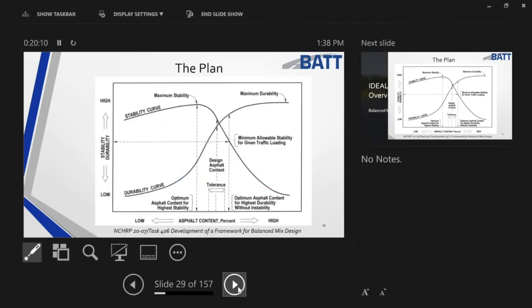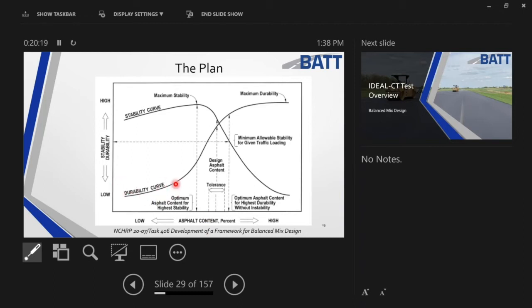This is going to show you the stability curve starting out really high and the durability being really low. If you look at the bottom, I'm looking at asphalt content as I move left to right. As I move to the middle, you see that balance coming together, just like I demonstrated with real data. And as I move to the right, my durability picks up. My mixture is more crack resistant. However, I begin to lose stability if I go too high. So what they consider looking at in the balance is being right in the middle, where I can have good stability, good durability, without sacrificing those two categories.